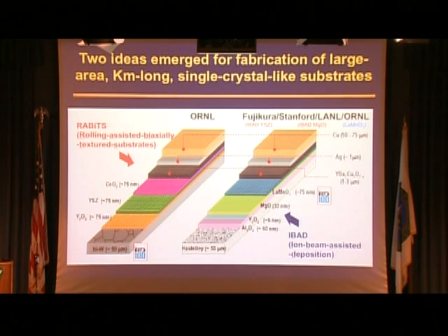Then we deposit the superconductor, which also has the same atomic orientation as the metal substrate, and hence it's single crystal-like. In the second case, called ion beam assisted deposition, we start with a metal which is not textured, and a few layers are deposited, which are actually amorphous for planarization purposes. Then a single layer called the IBAD layer is deposited, which actually is single crystal-like. Another buffer layer goes on, and then the superconductor.